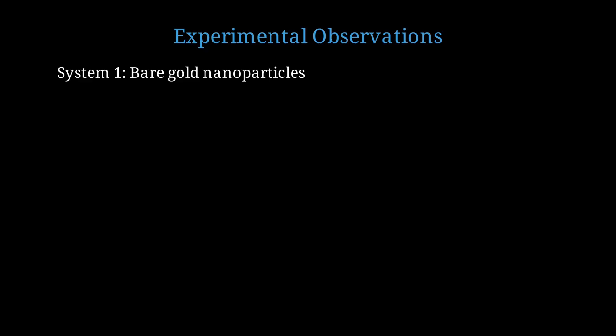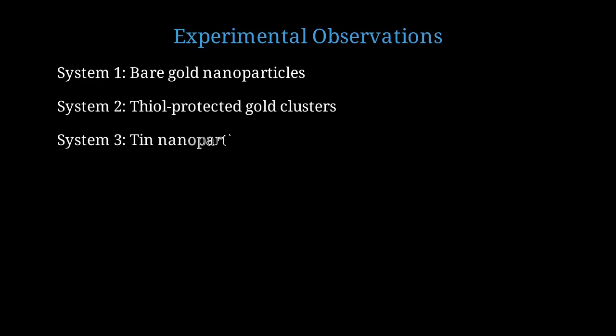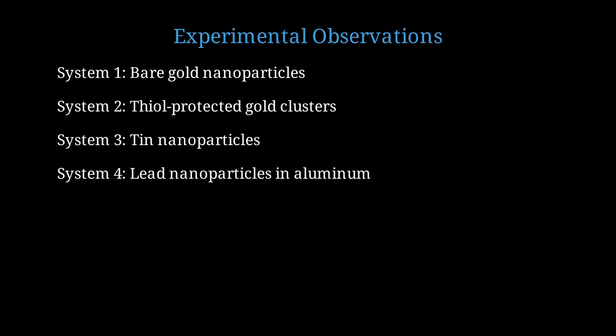What do experiments actually show? Different nanoparticle systems exhibit wildly different behaviors. Bare gold nanoparticles show classic melting point depression. A 2 nanometer particle melts around 600 to 700 degrees Celsius, much below the bulk value of 1064. But thiol-protected gold clusters of similar size can have melting points at or even above the bulk value due to strong ligand stabilization. Tin nanoparticles embedded in aluminum matrices show melting point elevation due to compressive strain from the matrix. Lead nanoparticles in aluminum show depression because the lattice mismatch creates tensile strain. Bismuth nanowires can show elevation due to quantum confinement effects that stabilize the crystalline phase.